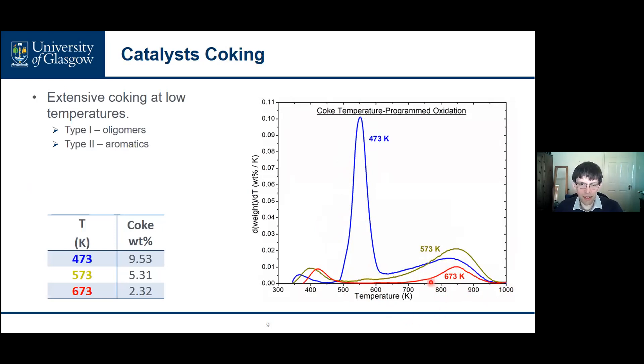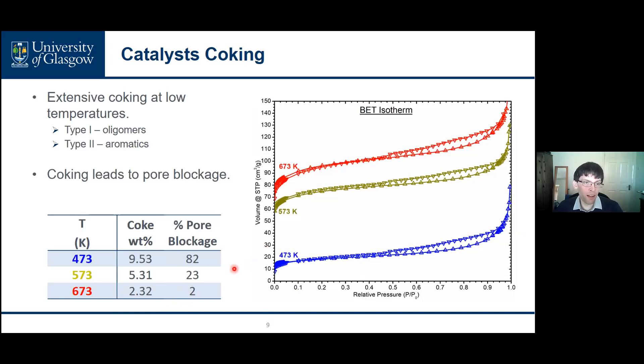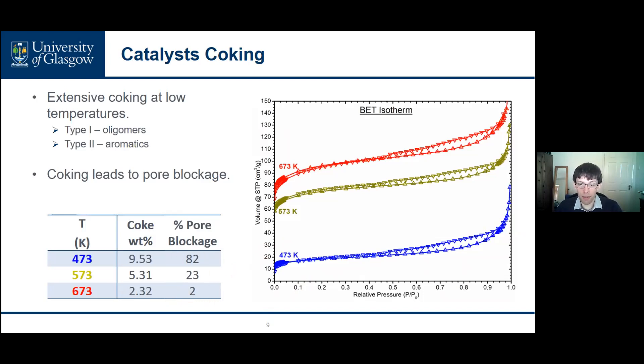This coke buildup is reflected in the porosity of the zeolites as measured by gas isotherm measurements. Coke formation at the highest temperature accounts for only two percent of the final catalyst, which is not significant enough to block the zeolite pores. While the high levels of coke production at 473 K result in near total blockage of the zeolite pore network, which explains the deactivation observed in the propene conversion data, since if access to the pores is blocked the propene cannot reach the active catalytic sites.